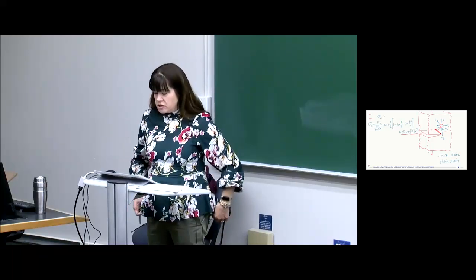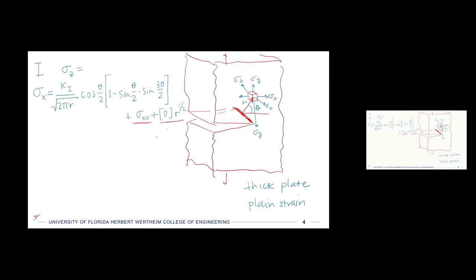And r is usually quite small. So this term here is actually a higher order term that usually goes away. And most textbooks actually will just omit this. They don't even have it in there. And if we don't have anything in the far field, then it simplifies down to just that first term. Okay, so that would be in the x direction.